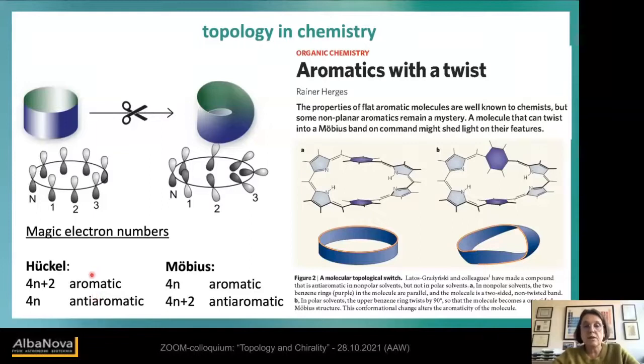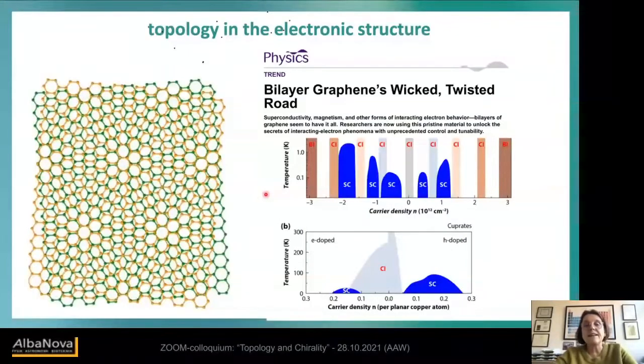So this is also strongly related to topology, and if we make a twist in the molecule, these rules are inverted. So now a benzene-like ring with a twist would be anti-aromatic, so the electrons would be localized, while if we had 8 electrons and 8 carbon atoms, it would be aromatic. And it's possible to make this by synthesis, so we can make these molecules, and they have really distinguished properties simply by giving the whole molecule a twist. And this again makes a very nice bridge to twisted graphene. Here we can take these giant aromatic molecules, and we take 2 layers of them, and this can even be chiral, so we can twist it in one direction and the other direction. So we can make a crystallographically chiral crystal out of this.